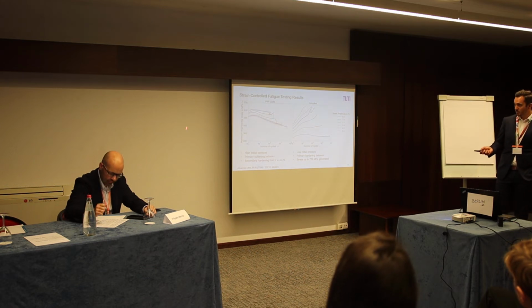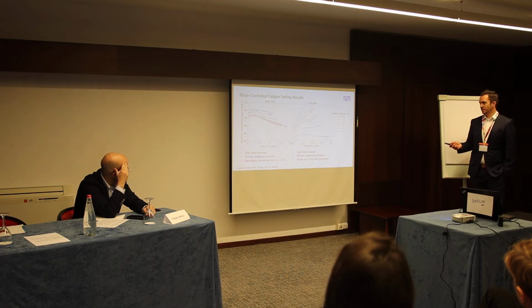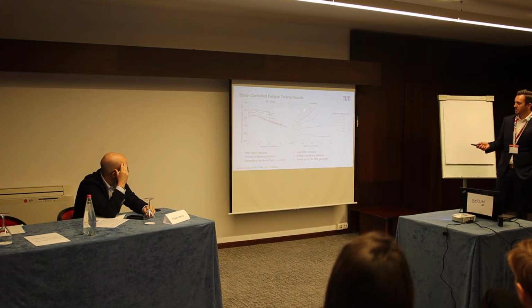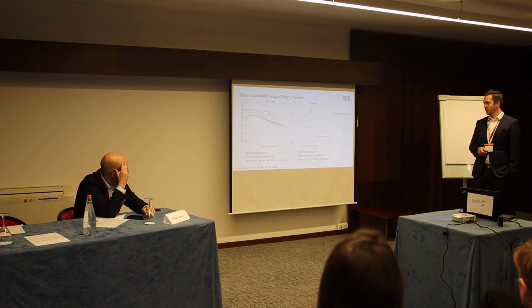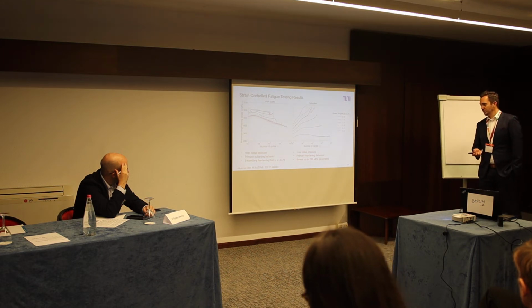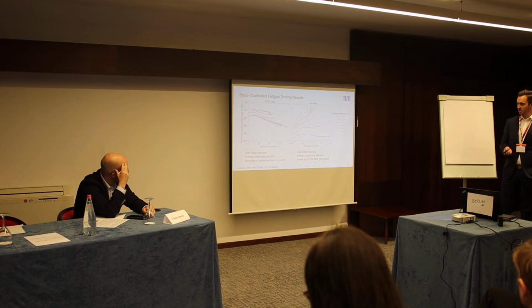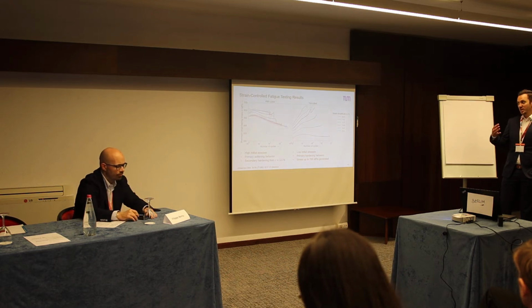Here we compared the number of cycles versus the maximum engineering stress in megapascal. On the left side you can see the PBF-LB process, and on the right side the hot roll process. The different colors indicate the different strain amplitudes, which you can see in the legend. What we could see for the PBF-LB process is that we have high initial stresses, followed by what I would call an initial hardening, but the main mechanism, or weakening in this case, was a softening behavior.